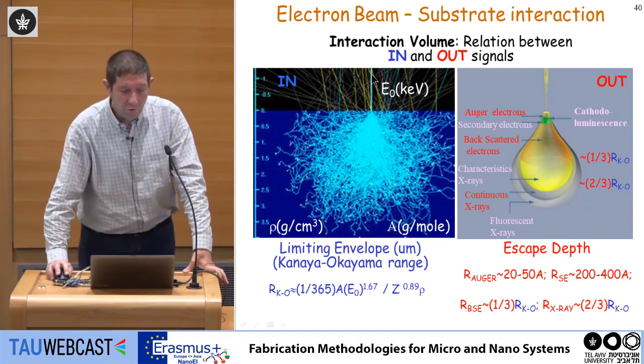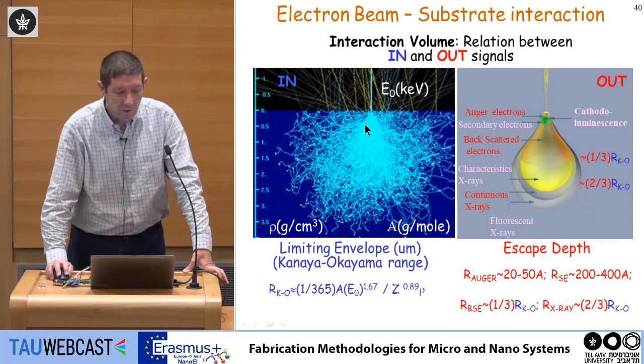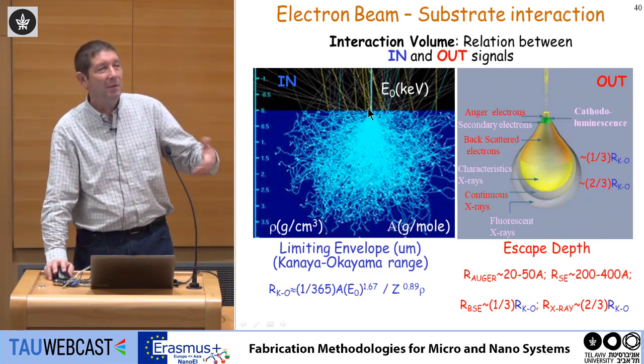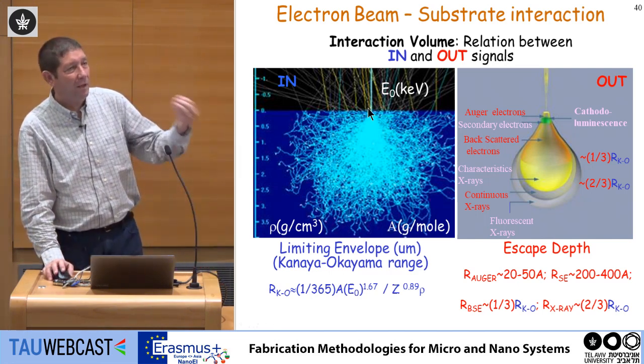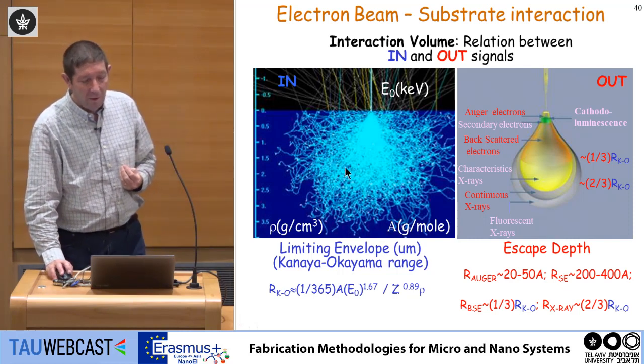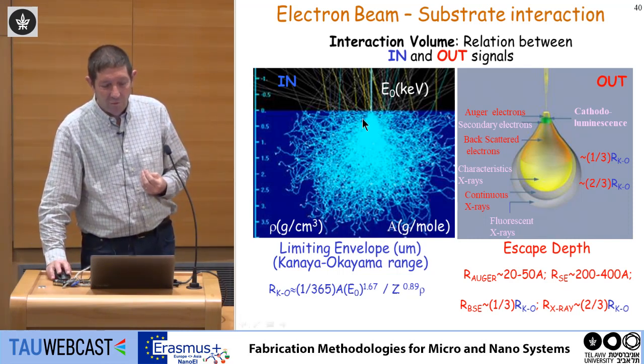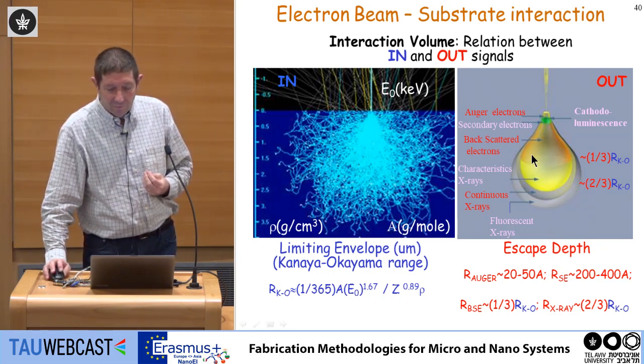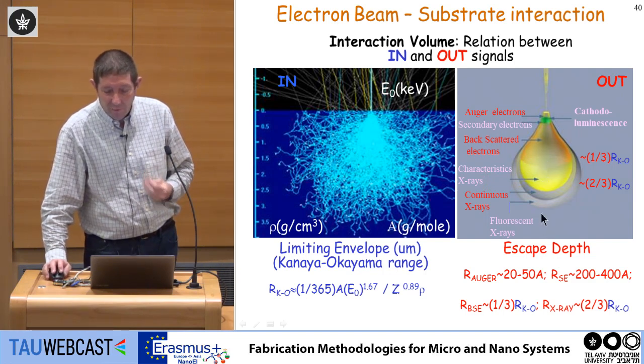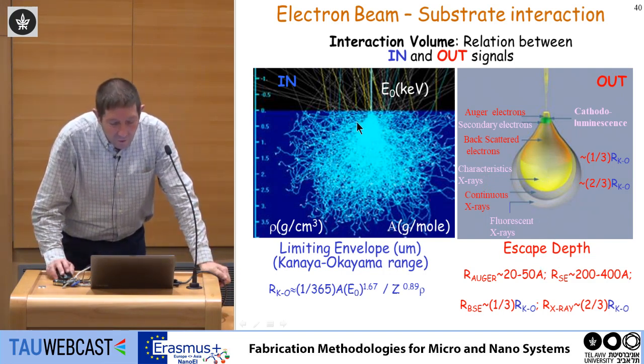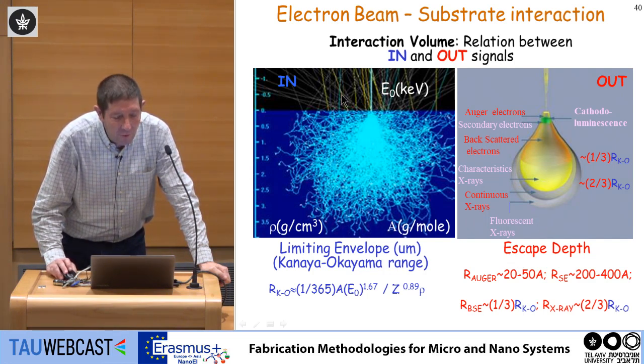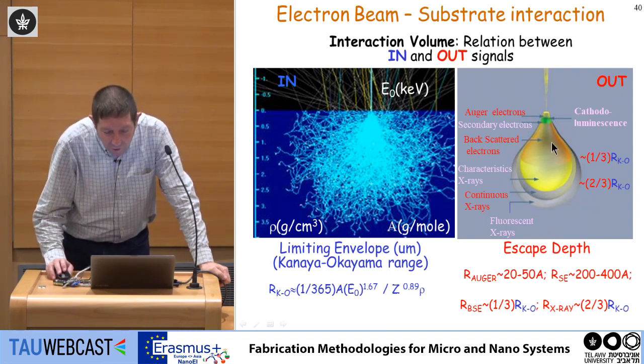With these tools, you shoot electrons, and then you have one, two, three, four, five collisions, then it stops, so you can simulate the interaction of the electrons or the ions with the solid. And when you do this simulation, you find out that you have what we can call a radius of interaction. And you can look at this and define what I would call escape depth. So you have a lot of interaction here, much, much less at the outside. And some of the electrons can escape also in this direction, simply going completely out.